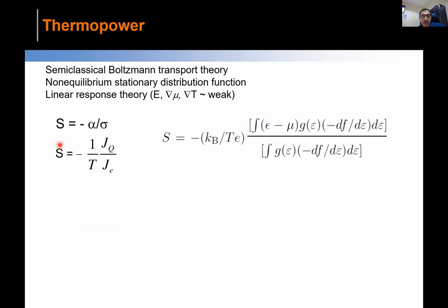What are the heat current and the electrical current? You can write them in terms of this equation. The heat current is nothing but some density of number, how many particles are moving, multiplied by their energy. So this is this term, around the chemical potential, you have E minus mu. This is your density of states, and everything is happening around the Fermi energy. So this is the derivative of the Fermi function and this term. And this denominator is nothing but your electrical conductivity. So this ratio basically decides what your thermopower should be.